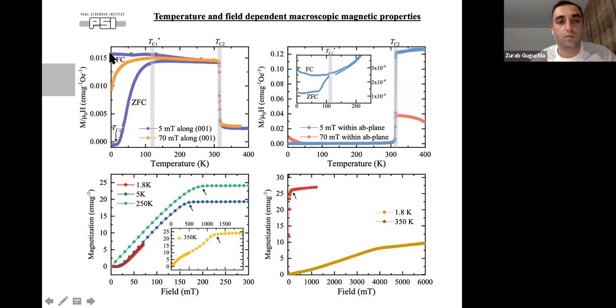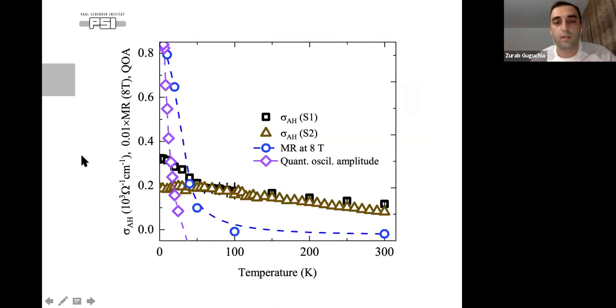And as soon as we do a field cooling, then we align the domains. While in this case, we have these dynamic magnetic domains, and then the whole effect is averaged out, so you don't register any hysteresis in the magnetization data. So these magnetic fluctuations can also explain this magnetization data. Now, as I've shown you before, we have this increase of magnetoresistance only across 120 Kelvin, and also the oscillation amplitudes, and all these, let's say, interesting properties happen at low temperatures.